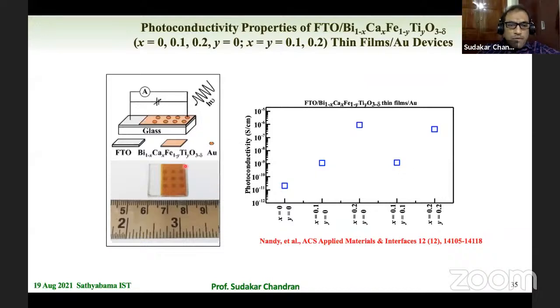So we made very simple devices. These devices, unlike the sensitized solar cells that I will discuss in some time, are very different. They are all solid state. You have a glass substrate on which FTO is coated. It's fluorine doped tin oxide. And on top of that, we make BiFeO3 thin films, and then gold contacts are given. Therefore, you can shine the light either from this side or from the back side, and find out the current generated, the whole current and voltage characteristics of the device. So these devices we tested also exhibit similar photoconductivity response that we found in bulk samples.